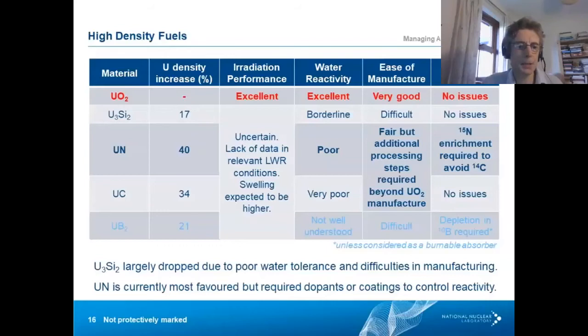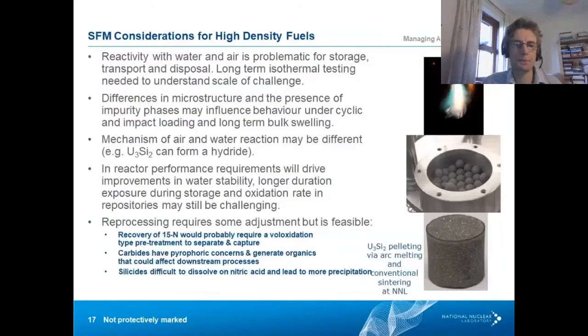These are much longer term prospects, as there are challenges both in the fuel development, manufacturing, and also in demonstrating compatibility with irradiation conditions. If we think about the back end, reactivity with water and air remain issues for storage, transport, and disposal. And although the temperatures are much lower under these conditions, the duration of exposure is also potentially much longer, and therefore behavior of irradiated materials under less extreme conditions needs to be understood. The mechanisms may also be slightly different, although that mainly relates to silicides rather than oxide and nitride forms. In reactor performance, improvements in terms of stability of exposure to water will automatically help the management of these materials in the back end.